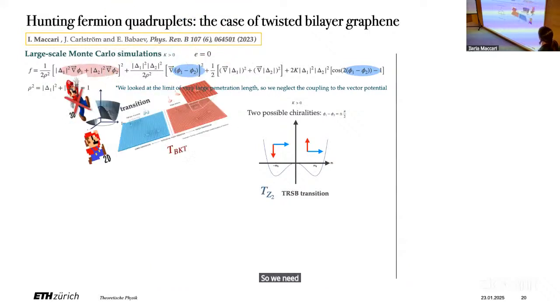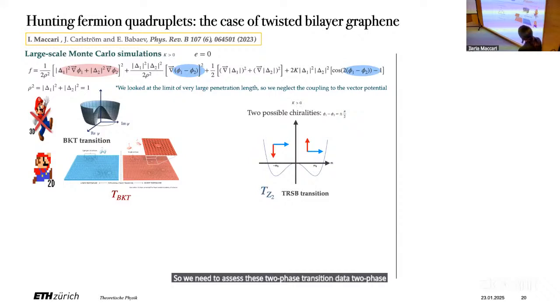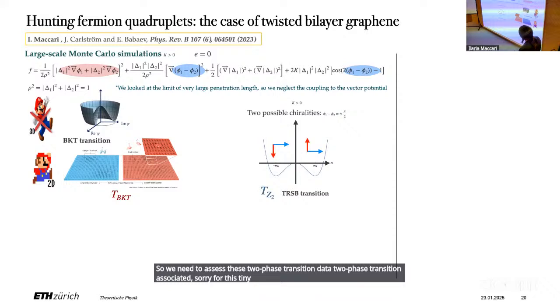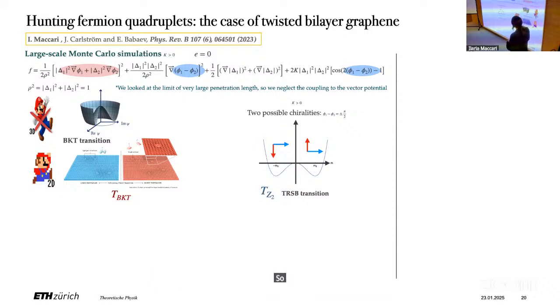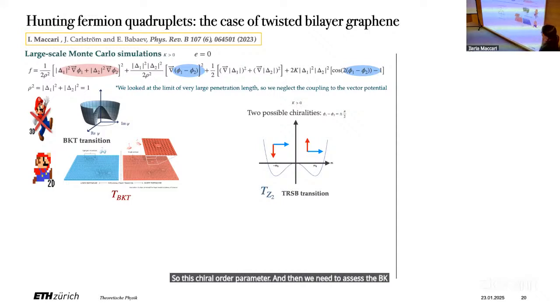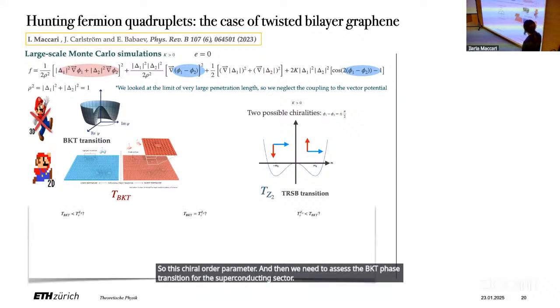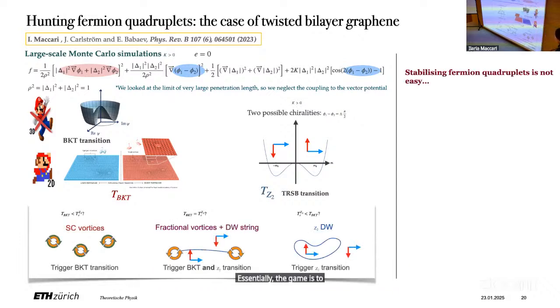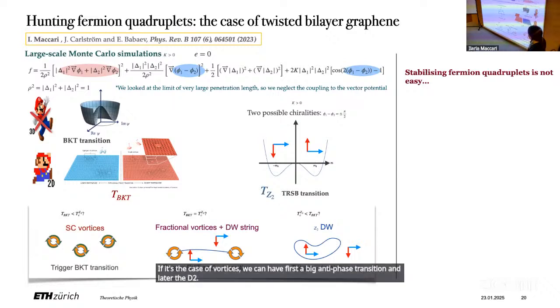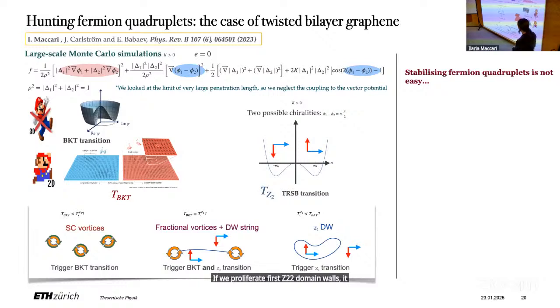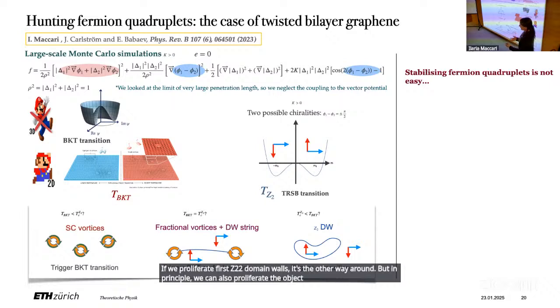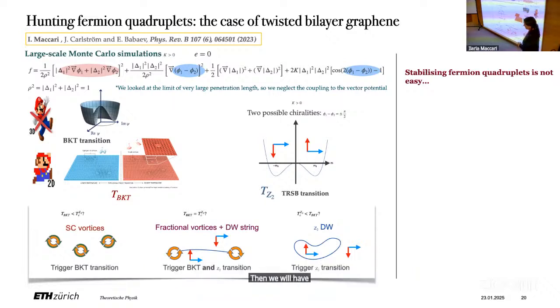So we need to assess the Z2 phase transition associated with the phase difference, so this chiral order parameter. And then we need to assess the BKT phase transition for the superconducting sector. Essentially, the game is to assess which of the possible topological excitations of the phase proliferates first. If it's the case of vortices, we can have first a BKT phase transition and later the Z2. If we proliferate first Z2 domain walls, it's the other way around. But in principle, we can also proliferate composite objects, which are formed by fractional vortices and these domain walls between the two possible chiralities of the two components. And if they are the first proliferating, then we will have a single first order phase transition.